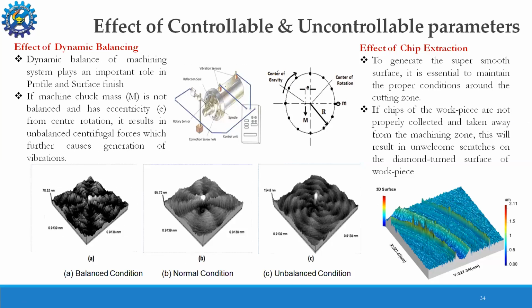Another two important parameters, these are also uncontrollable parameters. Dynamic balancing plays a very important role in maintaining a good profile as well as the surface finish. If the machine mass is not balanced and it has a certain amount of eccentricity from the center of rotation, then it leads to unbalanced centrifugal forces, which further lead to vibration. We did some experiments, and it can be seen that due to the unbalanced condition, vibration is generated and it deteriorates the surface roughness as well as the profile accuracy.